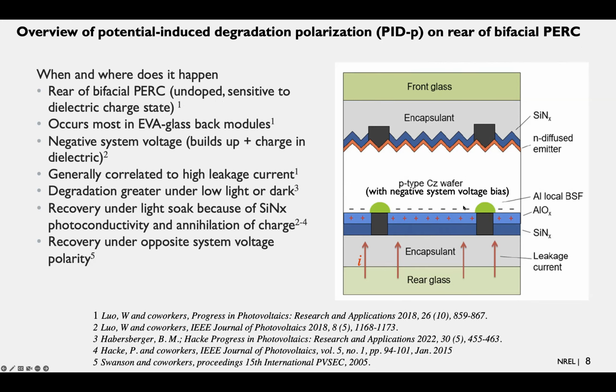So what we're looking at here on the right is a bifacial PERC cell with the rear passivating coatings of aluminum oxide and silicon nitride. And what happens is that any change in charge here, for example, if we see positive charge developing in the rear dielectric, that would attract minority carrier electrons from the base to it, leading to further recombination and annihilation of charge, leading to degradation of power performance and short circuit current and open circuit voltage.